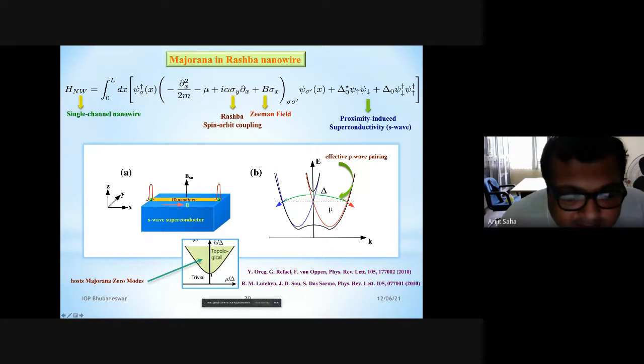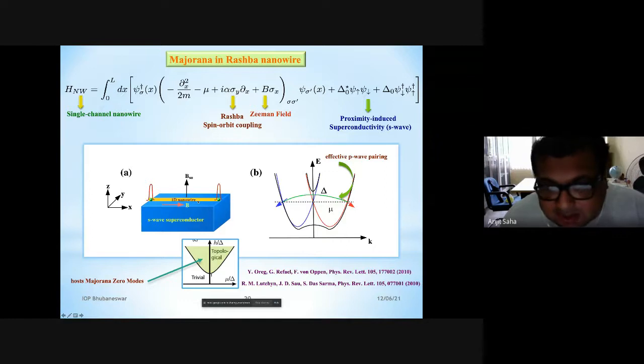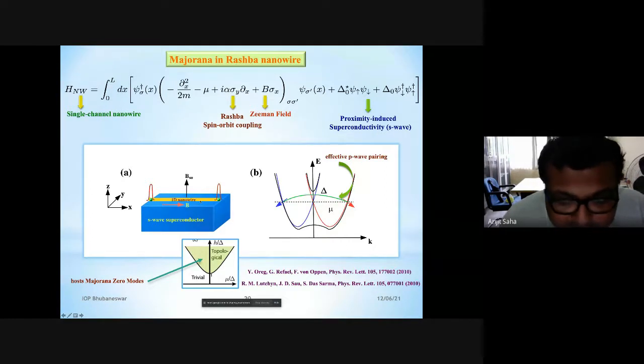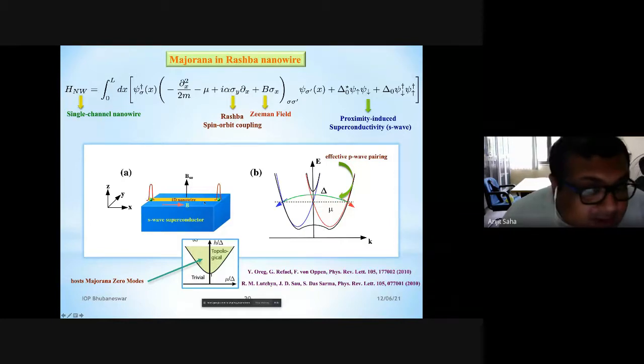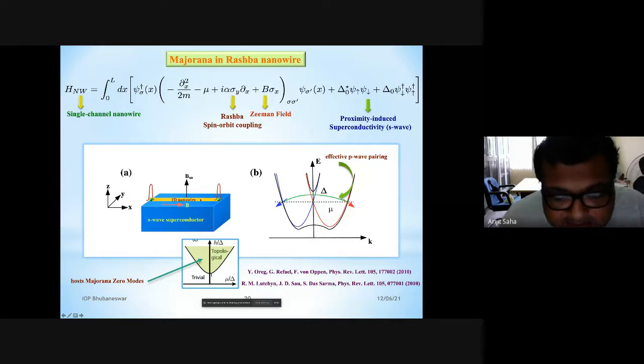Even if this material is not a superconductor, what you can do is place this nanowire in close proximity to a bulk S-wave superconductor. Then, due to the proximity effect, with the mechanism being tunneling of Cooper pairs into the nanowire, and depending also on how the interface is, you can actually induce superconductivity in this nanowire. But since it is an S-wave superconductor, S-wave pairing will be induced in the system.